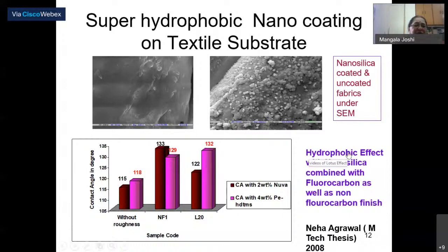As you can see, we have used SEM to see the deposition of nanosilica on the coated fabrics. You can see the picture, and definitely we have not been able to mimic nature. We can see the nanoparticles deposited on the cotton fiber, but they are not uniformly deposited. There are some aggregates, but definitely the effect has come.